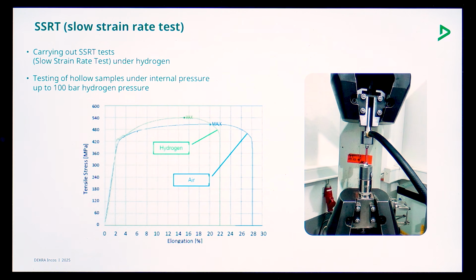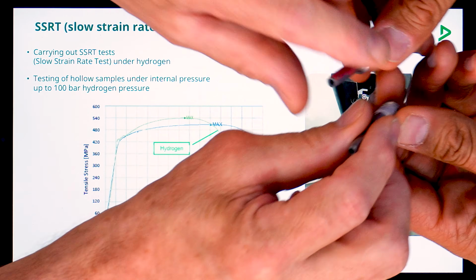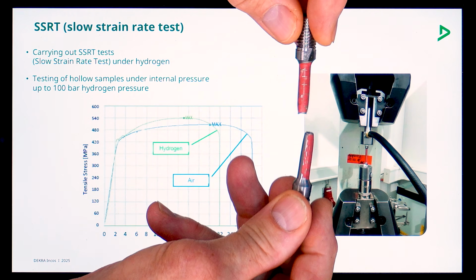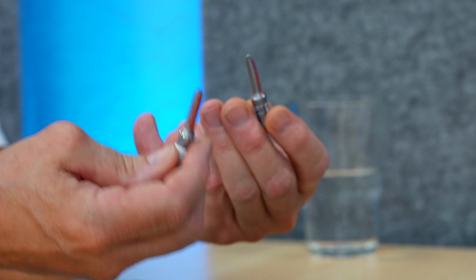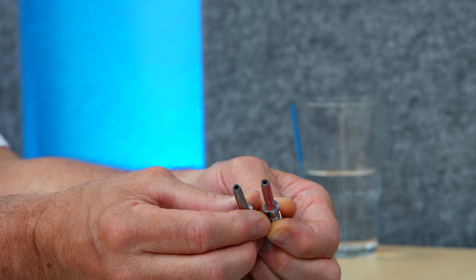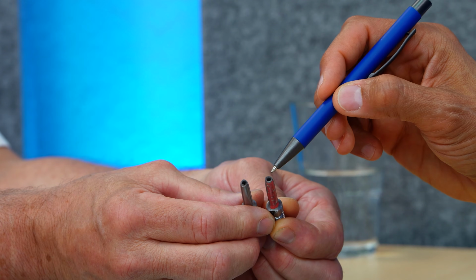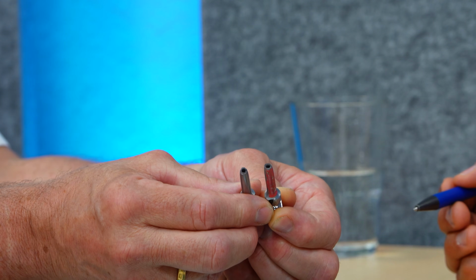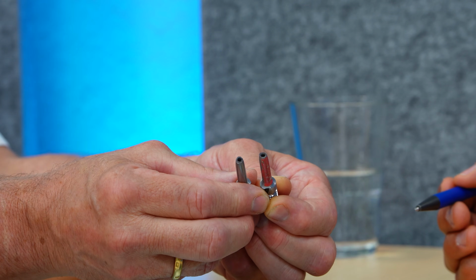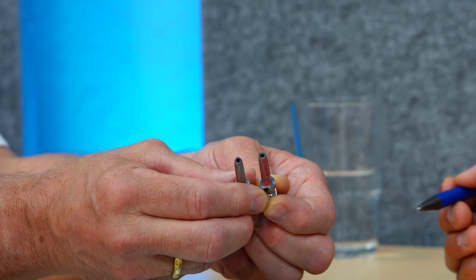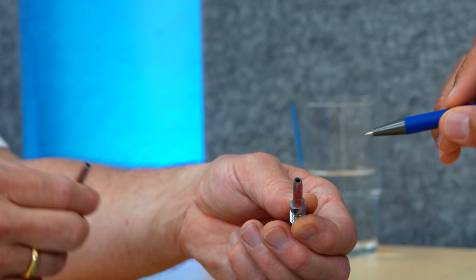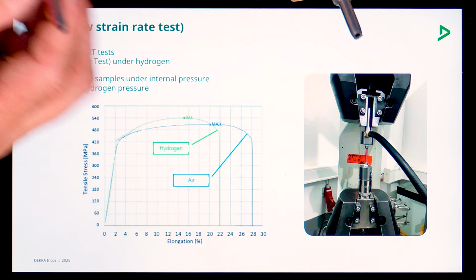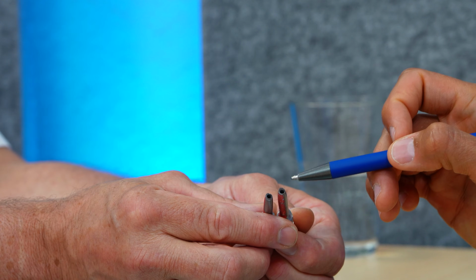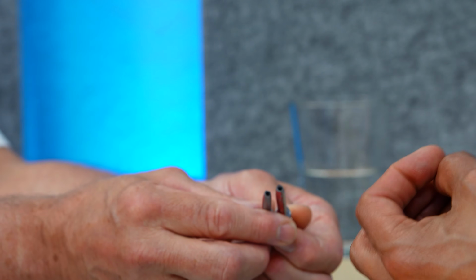Okay, cool. So here we see one of your test setups. This one we've already seen earlier. The special thing about these tests is that the samples are drilled, so it's like a pipe. During the test, this sample is filled with 100 bar hydrogen. The test is a so-called slow strain rate test. So there is hydrogen flowing through there as you pull the pipe during the test.